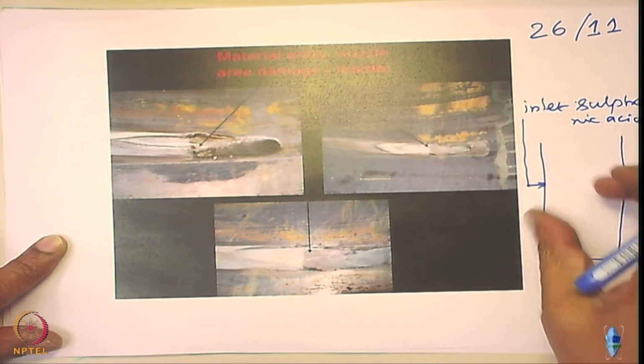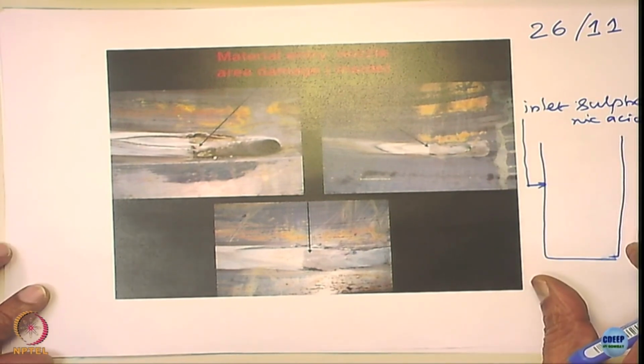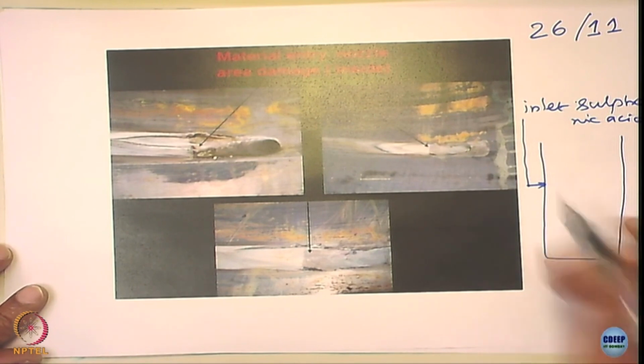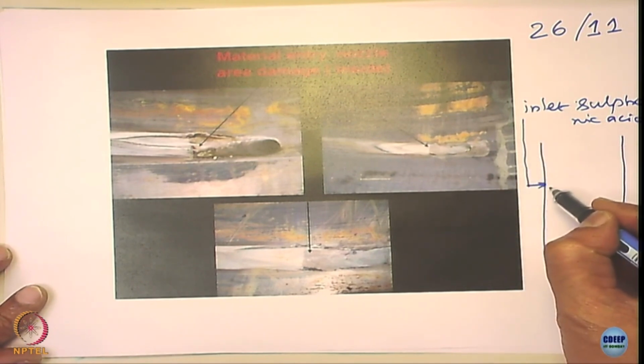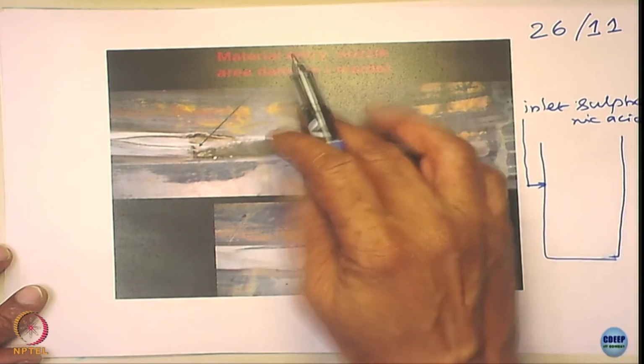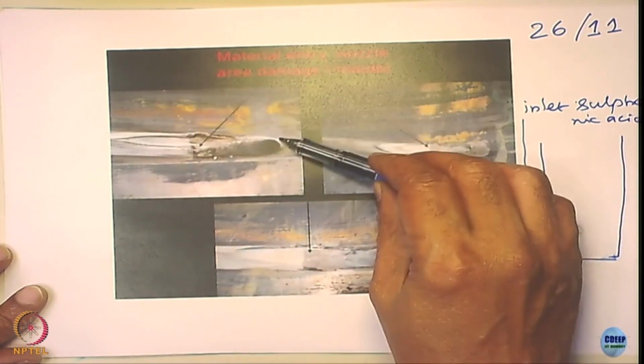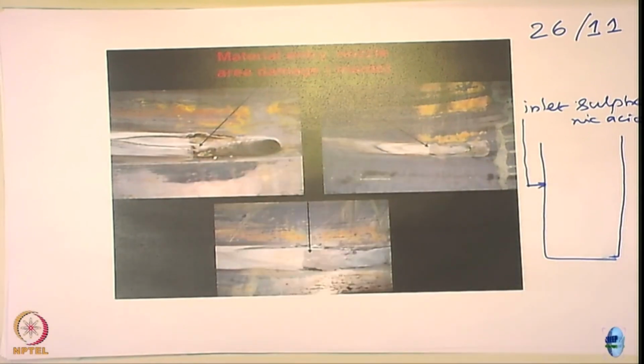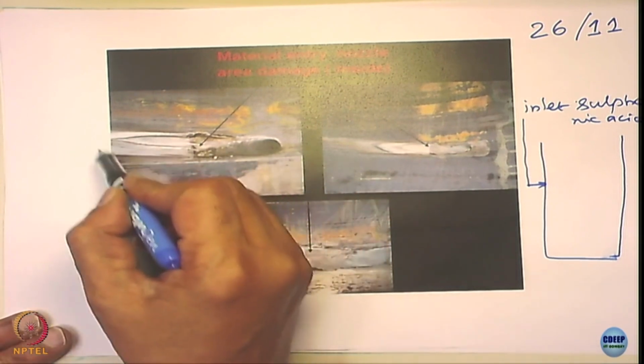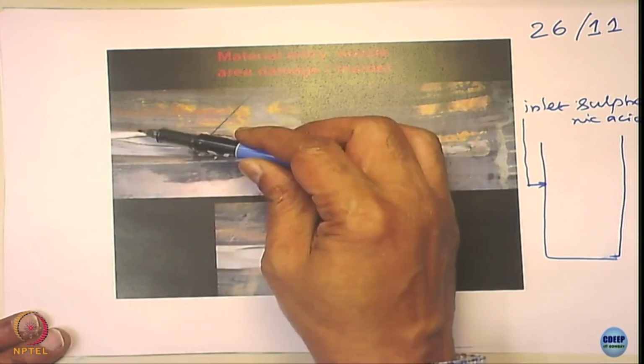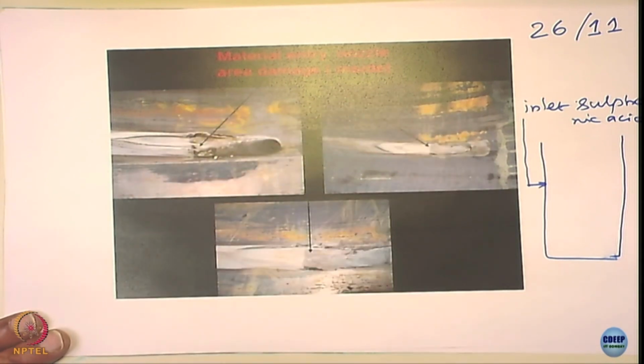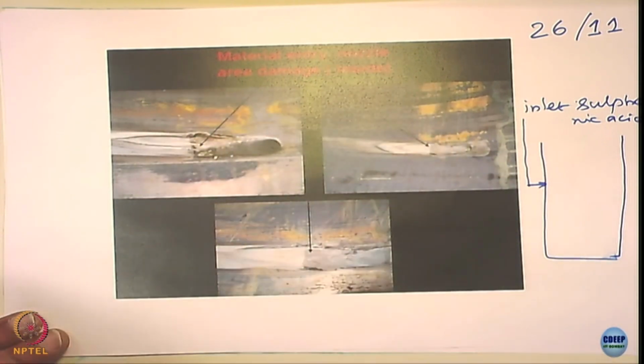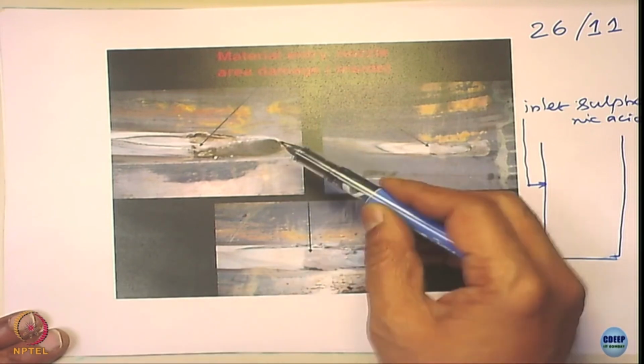So this is the reaction vessel, a kind of autoclave, you can call it a reactor. Through this the sulfuric acid is pumped. This is the surface of the reactor, and the sulfuric acid travels like this. You can see the marking here, severe corrosion taking place. Next to that there is not much corrosion, for two reasons. One is the velocity. The second is that the sulfuric acid gets diluted, so the corrosion rate also comes down, sulfuric acid here.